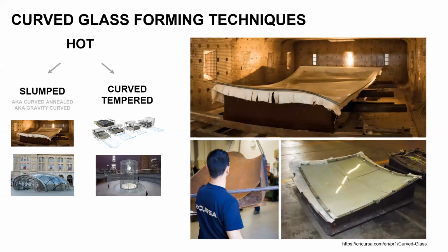Starting with slump glass, basically the process consists in placing the flat float sheets of glass onto a mold that's typically made of steel, protected by some fiber meshes, so that you can allow the glass to slide onto the surface as it's slowly softening, and then putting it into a kiln. So typically the limitations are going to be the size of the kiln itself, but also the thicknesses of the glass.